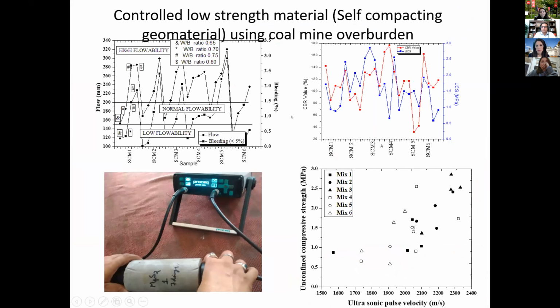As already we have discussed, geoenvironmental is a very broad topic. It's not confined to only geotechnical engineering. So when I'm talking about self-compacting geomaterial, it is the same as self-compacting concrete, but of low strength. So I need to check all these things, flow, bleeding, and then also I need to measure the porosity. And I don't measure porosity in the other way, I measure with the ultrasonic pulse velocity. I'm not going into detail, but when I say I'm going for a particular use, there is always some research to be done, and that is the very broad area of geoenvironmental engineering.